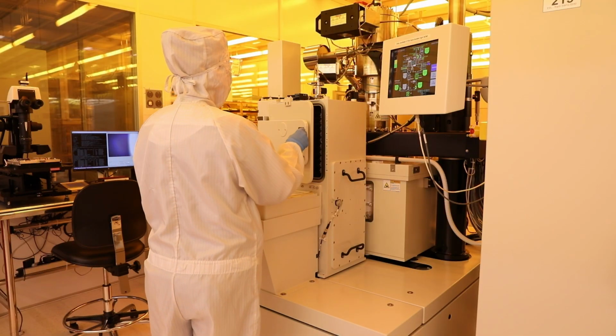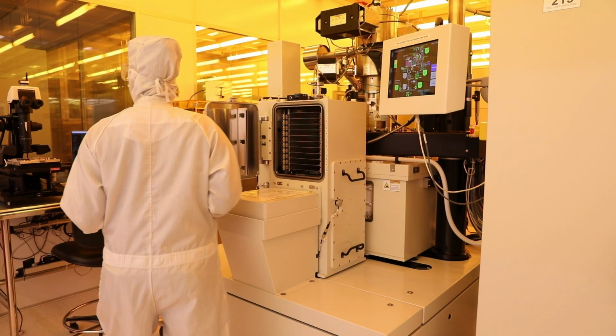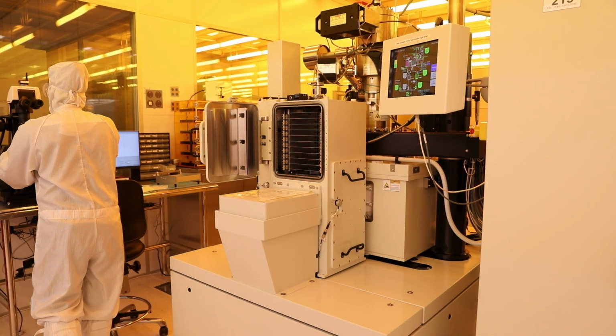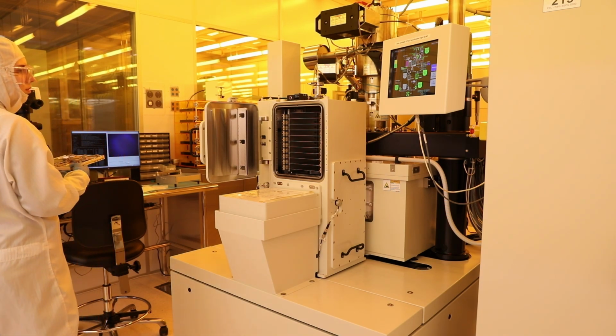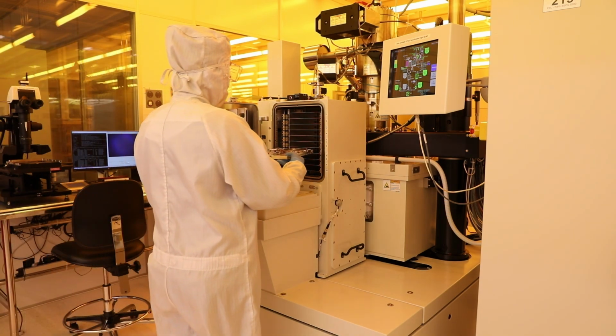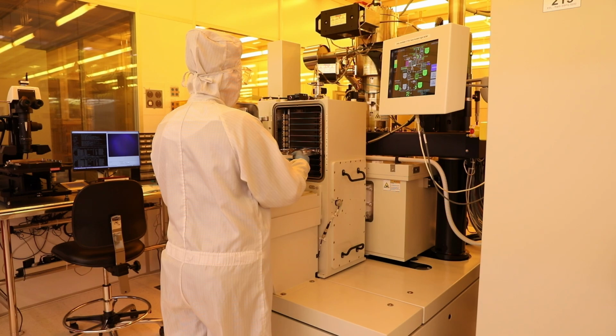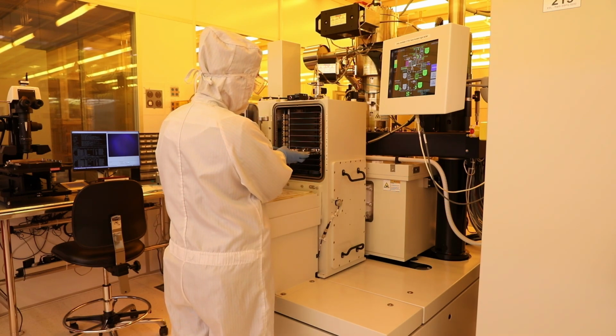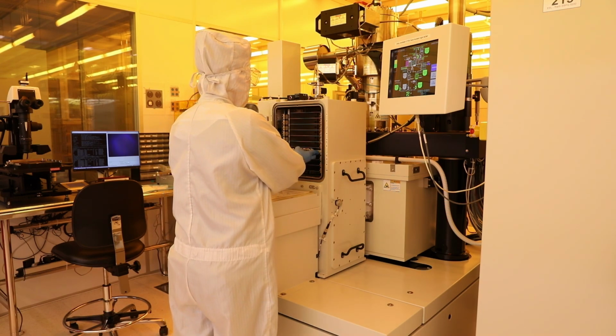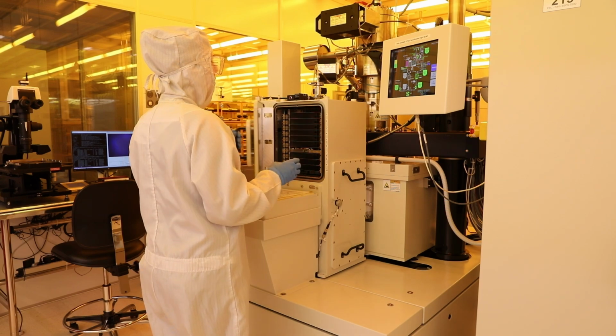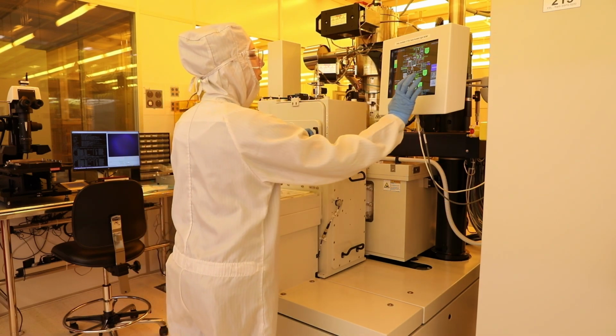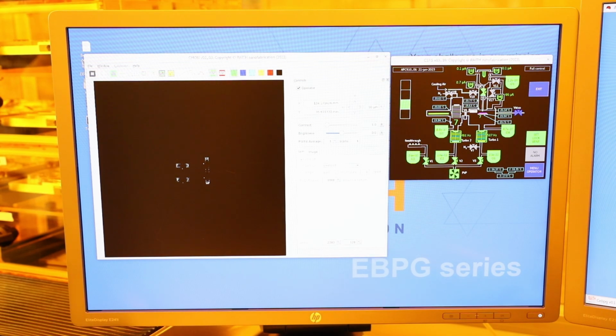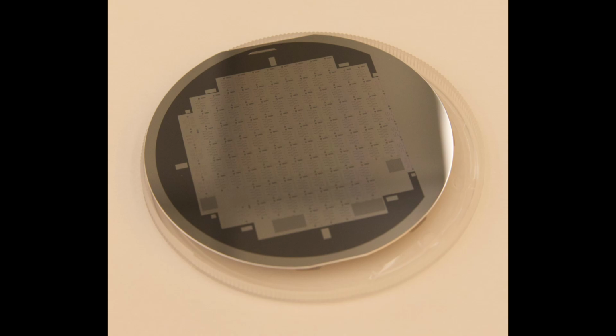Once the wafer is securely mounted onto the cassette, I can place it into the load lock of the e-beam system, which is then pumped down to a low pressure, and the cassette is transferred onto the writing stage of the system. Unlike with the laser writer, we will not be able to see directly what's happening inside while the pattern is being exposed, because it needs to happen in a shielded chamber. But we can monitor the effects of the electron beam firing on the screen, sort of like with an electron microscope. Once the pattern is exposed into the resist, we can develop it in a beaker of developer, same as we did in the previous lithography step.